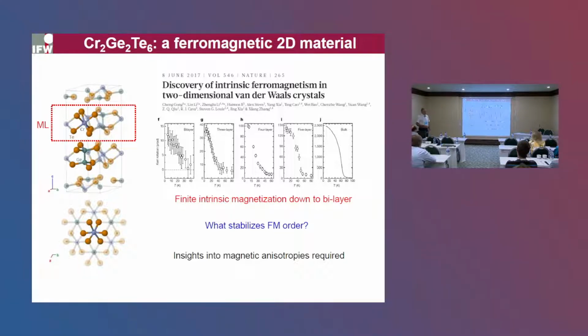That this material is a ferromagnet was known a long time ago. But recently, there was a really interesting work published in 2017 by Cheng Gong and co-authors, who showed that this ferromagnetic order present in the bulk, this is the magnetization of the bulk material at, say, 5 Kelvin, is still present if one reduces the thickness of the crystal. And the evidence came from the magnetic Kerr effect. So this is the magnetization of the 5-layer, 4-layer, 3-layer, and bilayer system, which still have a robust ferromagnetic magnetization. They couldn't measure the single layer because it was very unstable, but at least in the bilayer, the system retains ferromagnetic order.